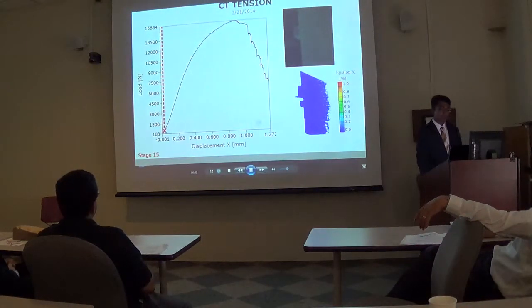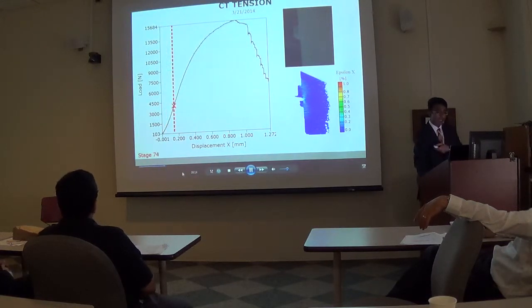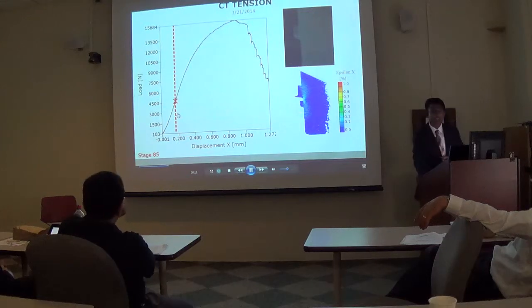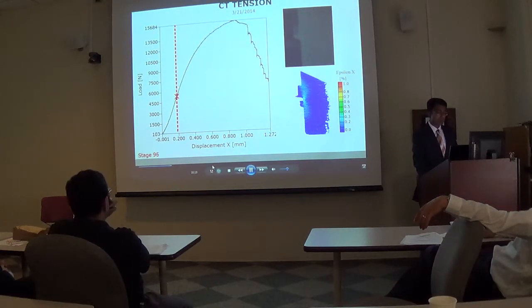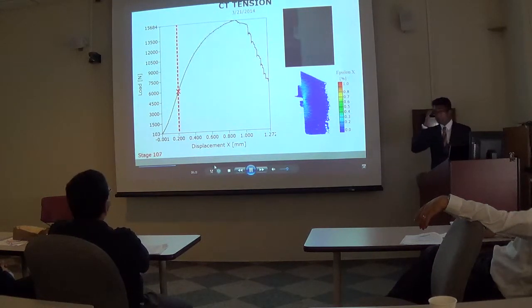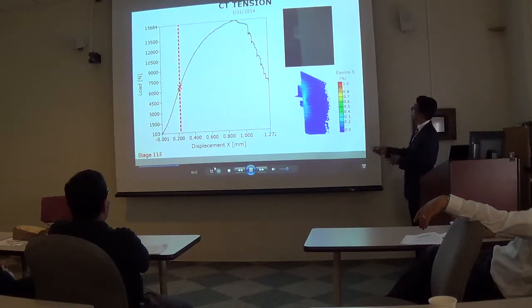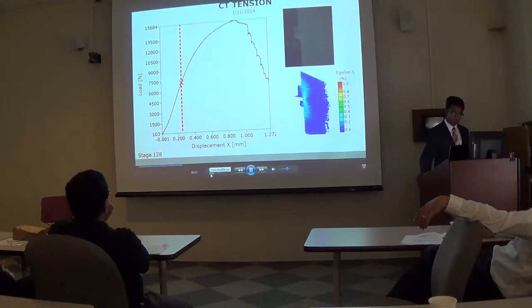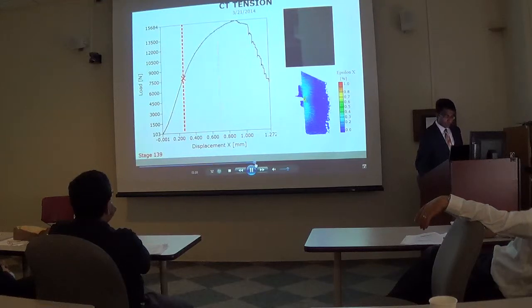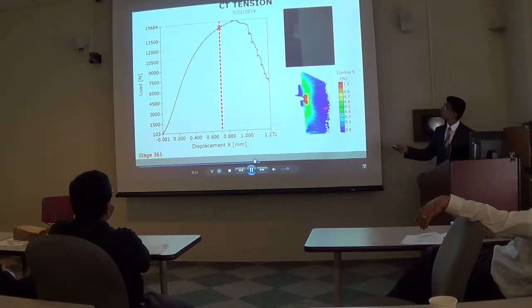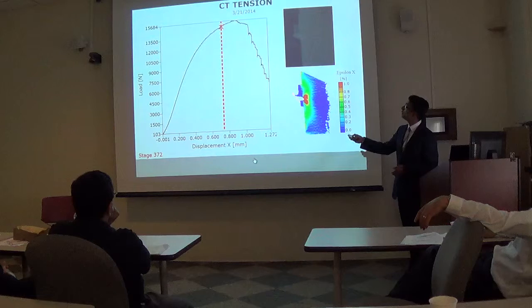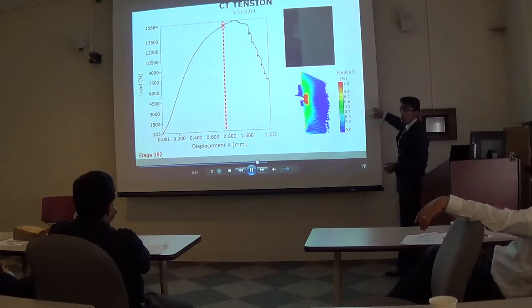So you can see as the specimen is being loaded, you can start to slowly see how strain accumulates around the crack tip, as you can see here. And with subsequent loading, you can see how the plastic zone increases, and the strain develops and increases in magnitude, also as seen here. With subsequent loading, you can see how the strain increases, and as it approaches the peak load, you can see how this plastic zone grows as well.